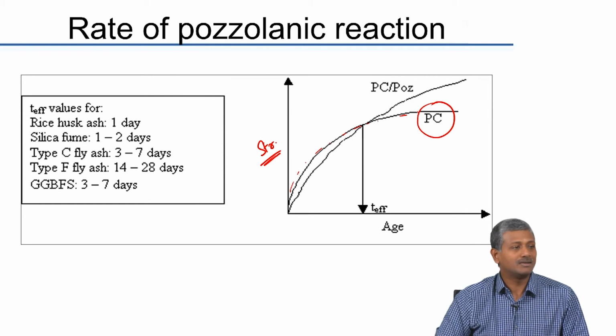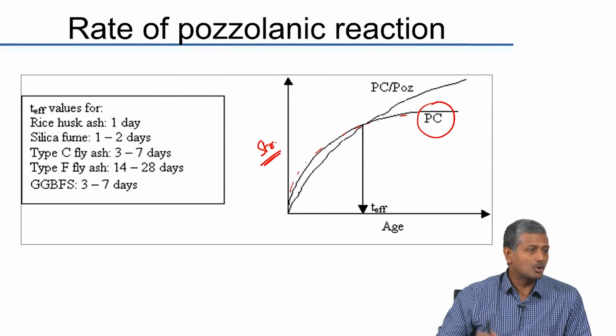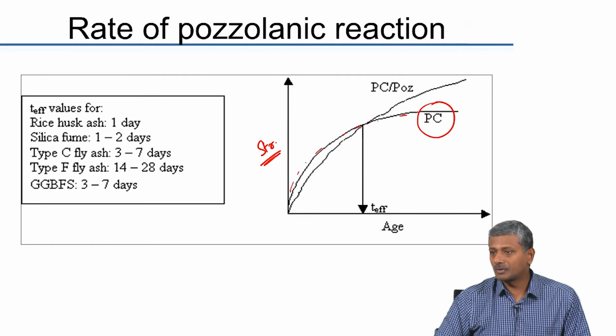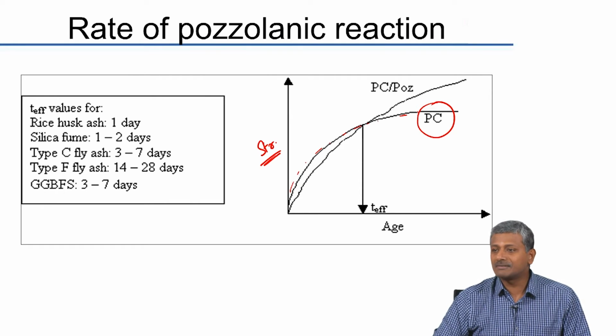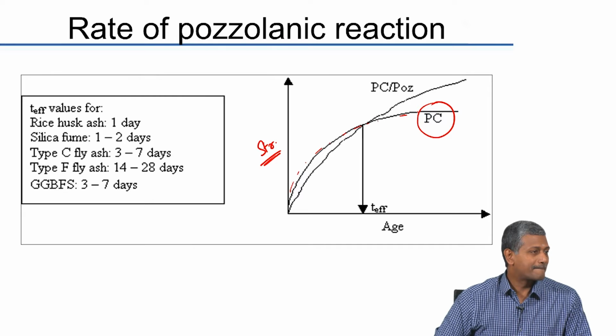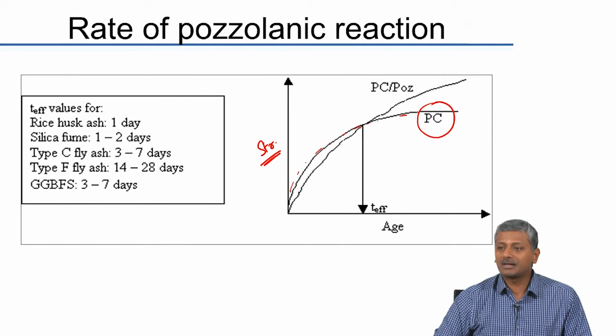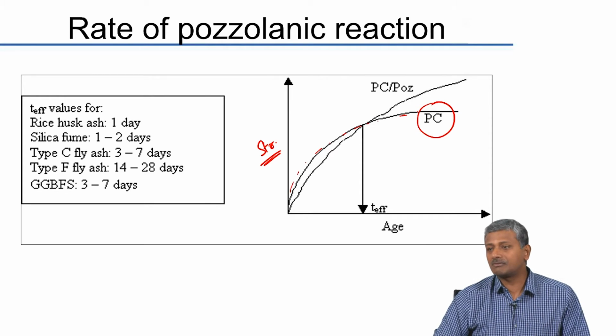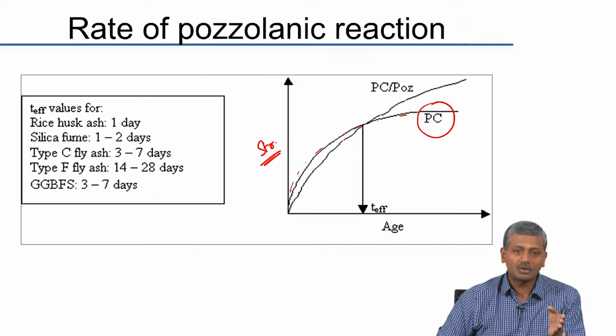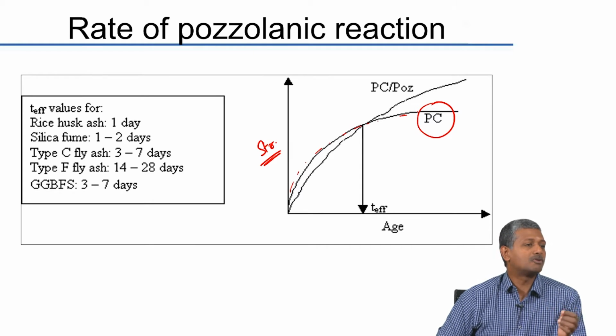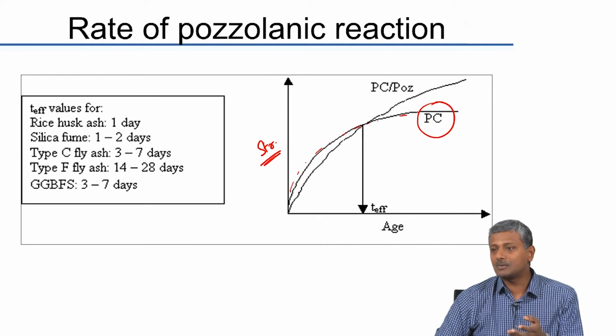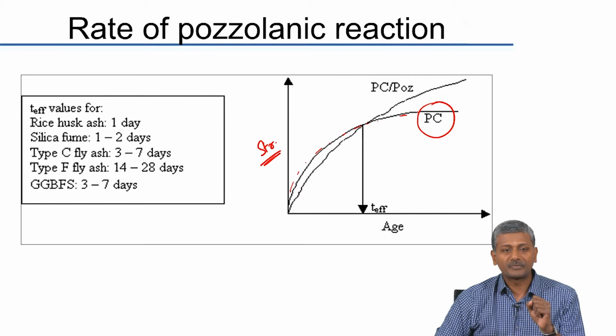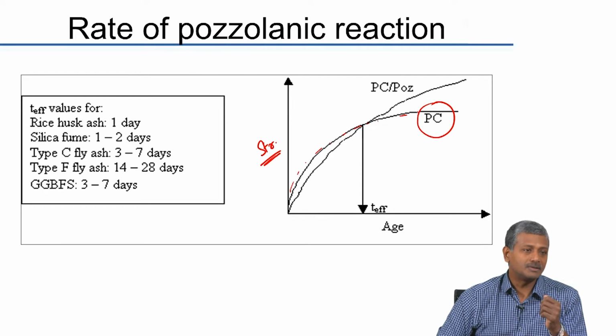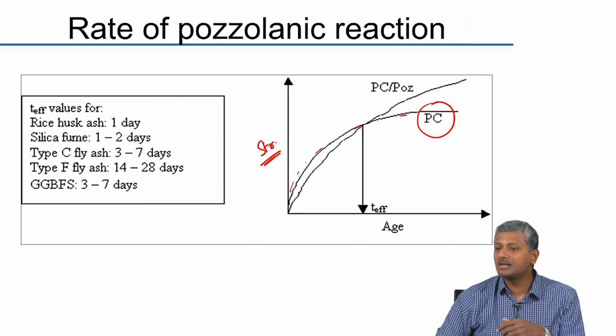Always make sure that you understand that any strength development will take place only as long as you continue curing. And then why do we stop curing for concrete at 7 days? Generally by 7 days we are getting nearly 70% of your target strength, and in today's concrete 70% of target strength more or less matches with the characteristic strength of the concrete itself. For example, if you are designing M30 concrete, your target at 28 days is around 38 to 40 megapascals. By 7 days you would easily reach around 30. So, once you have reached that strength, you do not really need to cure much more.